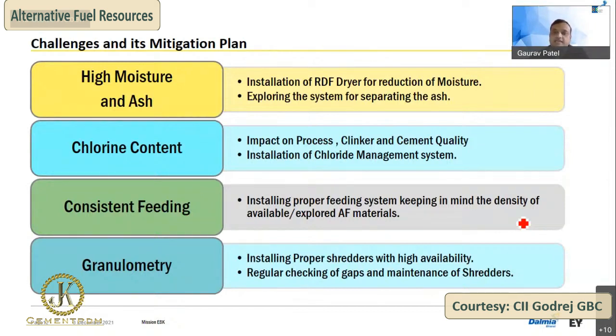For chlorine content, there's only one solution, which is to install a chlorine management system, like a chloride bypass system. Another challenge is consistent feeding. Even if we maintain moisture and ash within our criteria, if consistent feeding is not there, that will also have a negative impact on our system. And granulometry is the size, so proper maintenance of shredders and proper gap checking are also important in order to achieve our target of higher TSR.